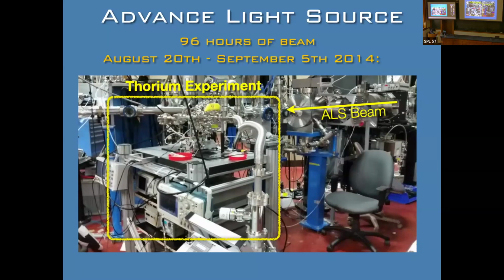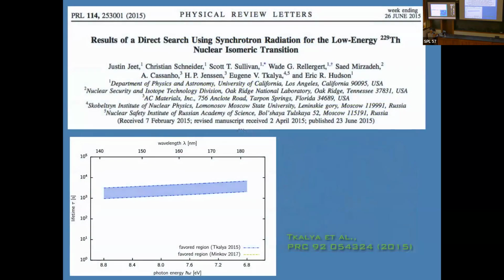It's dead simple. We were there waiting because we didn't know if these crystals would just fall apart after a day or two. We'd never really made anything like this before. And we didn't have that much thorium, so we didn't get a lot of shots. So the crystals were almost still hot from the oven when they arrived at the ALS, and we just ran and put them right in and started measuring. And we saw almost nothing.